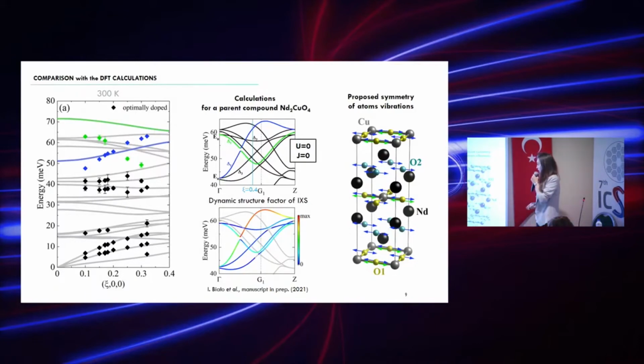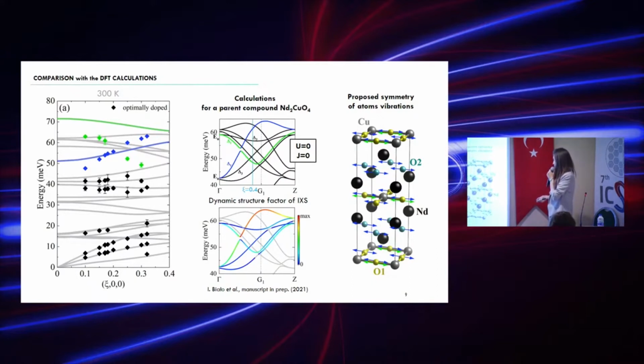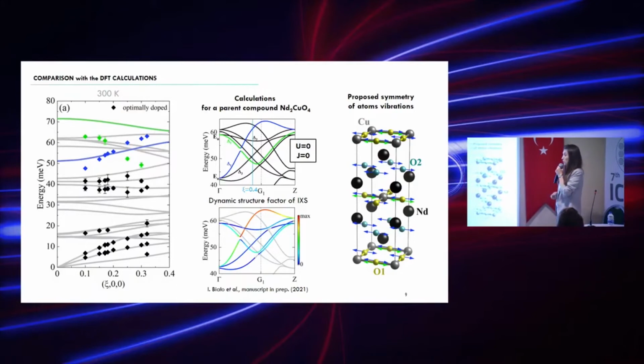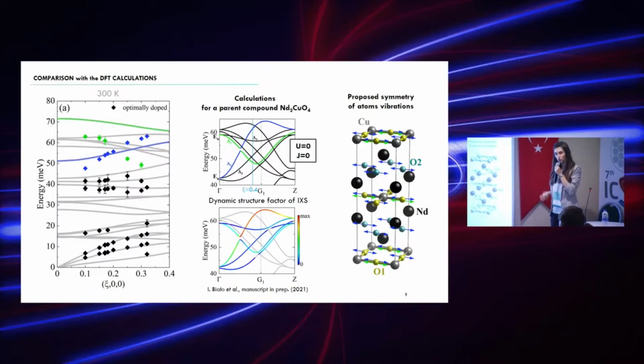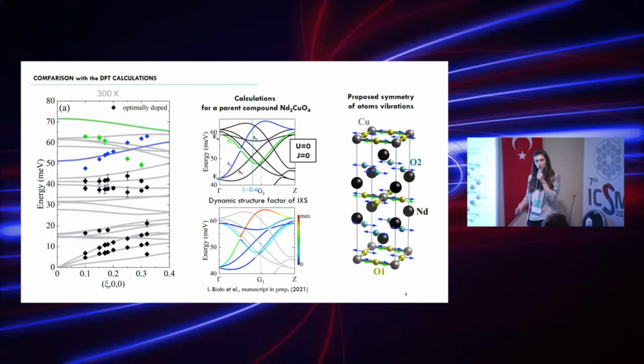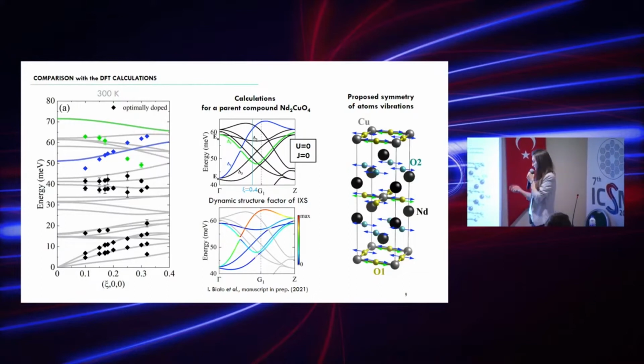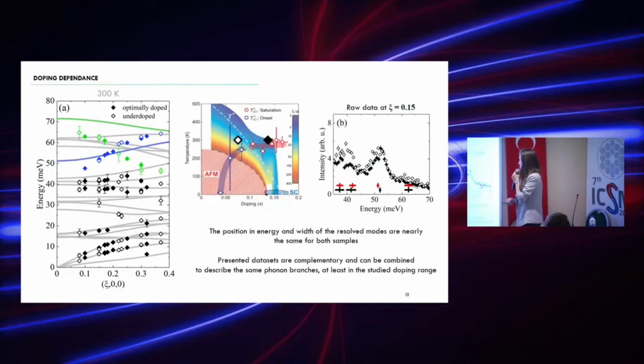And what I can say more about this vibration of atoms that we can observe here for these two branches is that the blue branch corresponds to the vibrations of all oxygen atoms, while the green mode corresponds to the vibrations of only oxygen atoms within copper-oxygen planes. So these are bond stretching modes. So we see that only oxygen atoms are involved in the vibrations which are drastically changed between undoped and doped material. That's kind of important information.